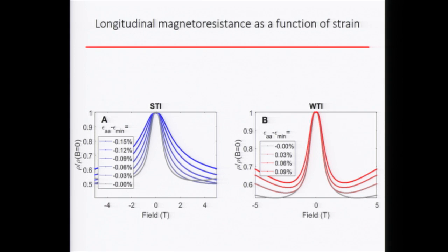Because the Landau levels of a topological insulator behave differently from an ordinary insulator, the last Landau level of a topological insulator will actually have an opposite energy dependence from the trivial insulator. So if you're in the quantum limit, and the field is enough to make the last Landau level cross, then you'll see some features that depend on which kind of topological state you are in. That could explain this, but you need finer measurements to resolve that.